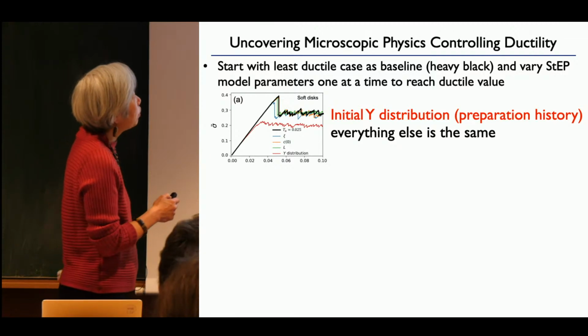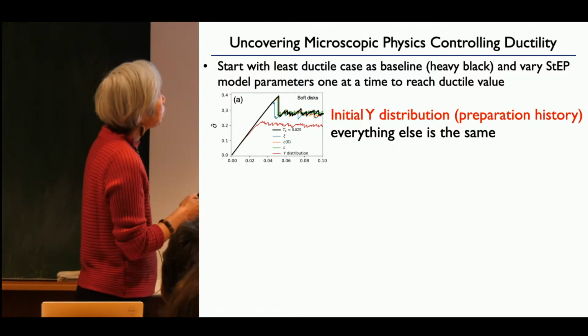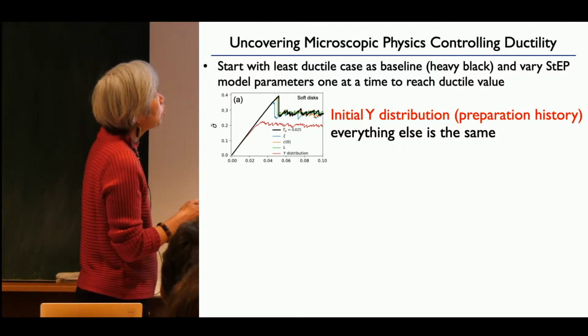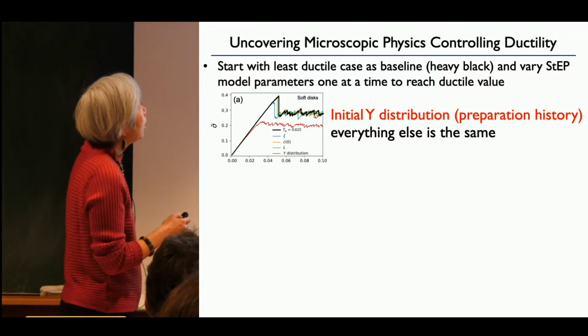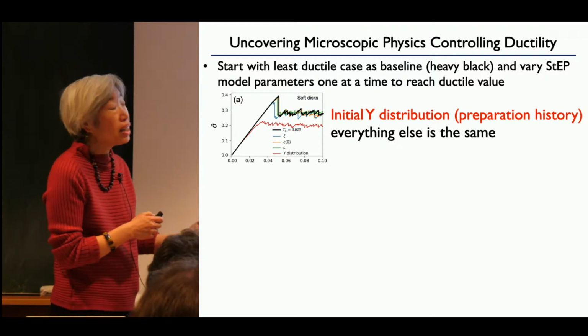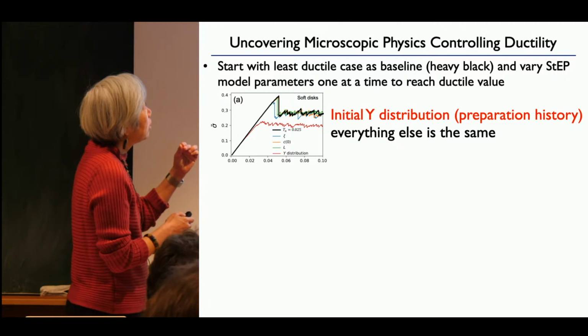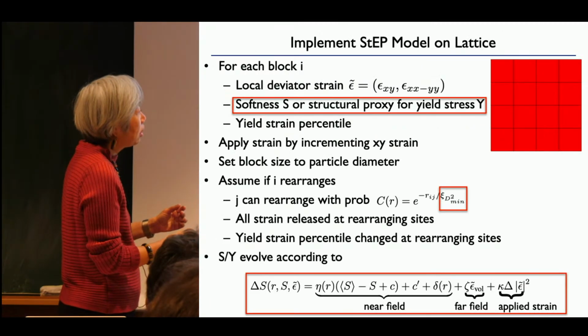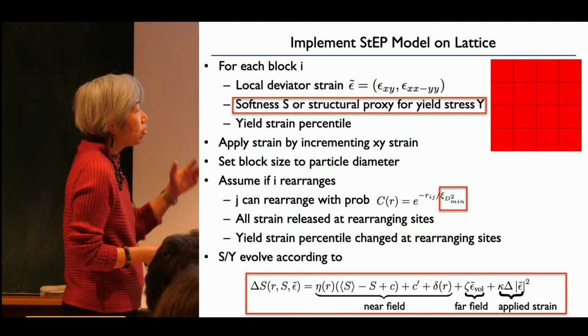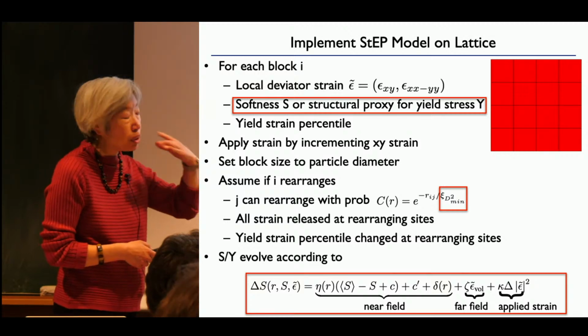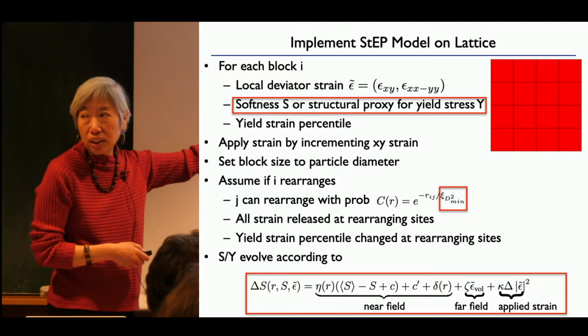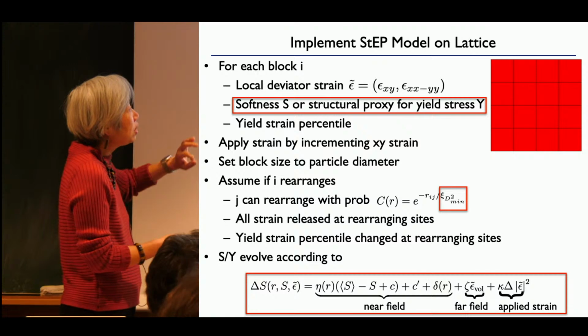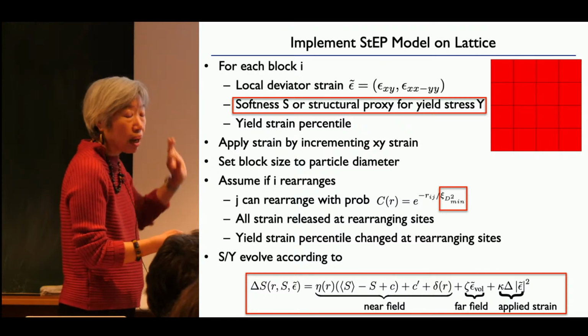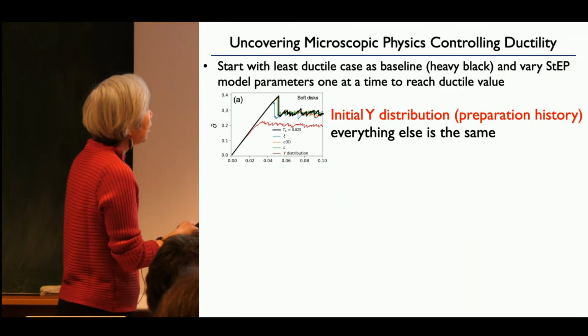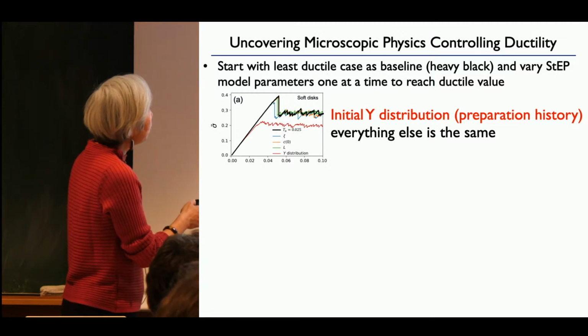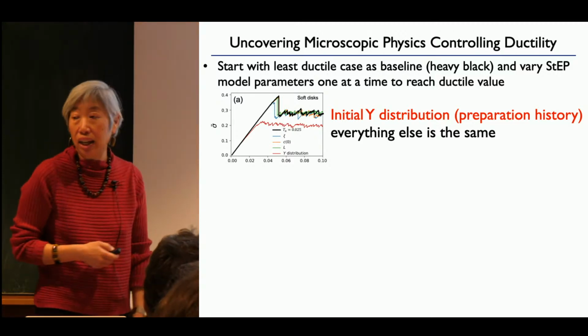So how can we look at this? What we do is we take the brittle system, the more brittle system in each case, and we take our StEP model results for that, and then we vary each of these things continuously between what we get for the brittle system towards what we get for the more ductile system. So all of these things, we just vary them continuously one by one, and we see what does it take then to see a stress-strain relation that corresponds to the more ductile case.